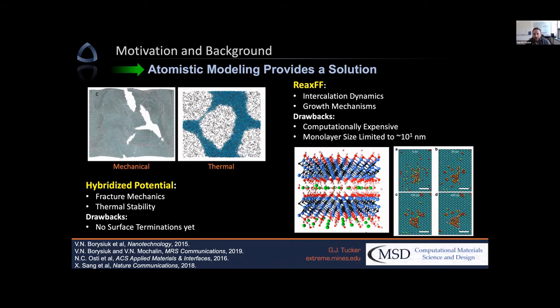These have been used very successfully to look at intercalation dynamics and growth mechanisms of different types of clusters and different types of MXenes. But here too, there are drawbacks. It can be computationally very expensive to run, orders of magnitude slower than other potentials. And if we were to think about studying a monolayer size, we're usually limited to the 10 to 50 nanometer range with a reasonable amount of computational resource.